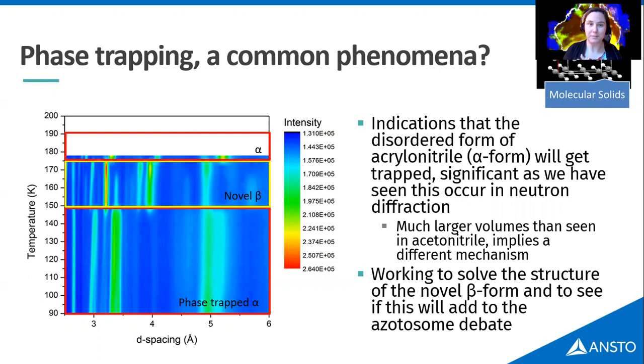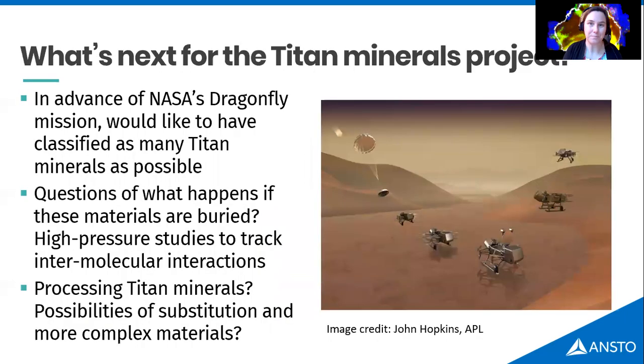And hopefully now we've cracked this and we've realized that this is what's going on, we can solve the novel beta form, which we believe is probably the more stable low temperature form. Although, of course, until we've got the crystal structure, we can't perform the optimization calculations to find out for sure. And we're hoping that once we've done this and we can look at the intermolecular interactions, we can really add something solid to this debate about the azotosome, which is that membrane that people have predicted in acrylonitrile. So that's another watch this space going on.